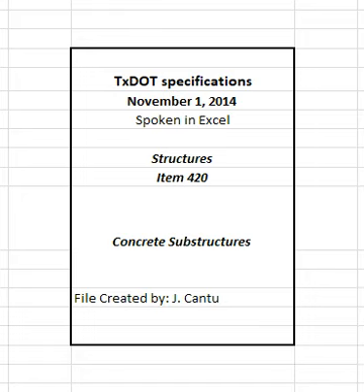4.10.2.2 Water spray. Overlap sprays or sprinklers to keep all unformed surfaces continuously wet. 4.10.2.3 Ponding. Cover the surfaces with at least 2 inches of clean granular material, kept wet at all times, or at least 1 inch deep water. Use a dam to retain the water or saturated granular material.